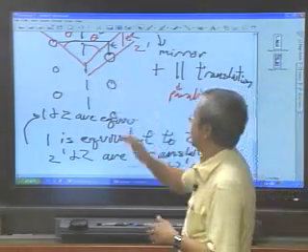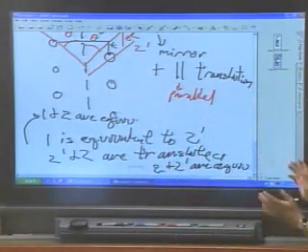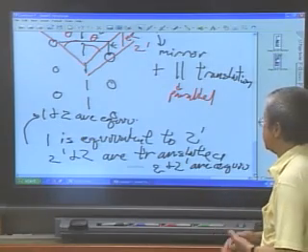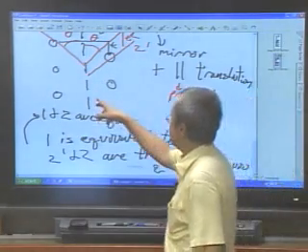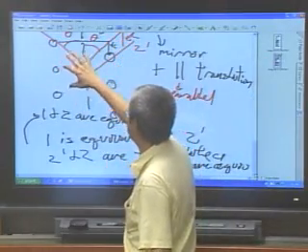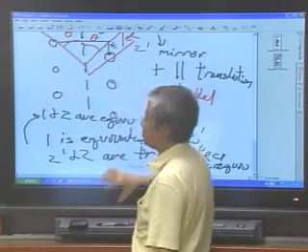So whether it's a glide plane or a mirror, it doesn't matter. Glide planes basically are treated like mirrors. That's why there are a smaller number of point groups. You don't need to distinguish. Which then raises the other question, well, why are you concerned about glide planes? Well, because if you have glide plane symmetry, you have 3 atoms here, then these 3 atoms are shifted. If you have mirror symmetry, you have 3 atoms here, and the other 3 atoms are right across.